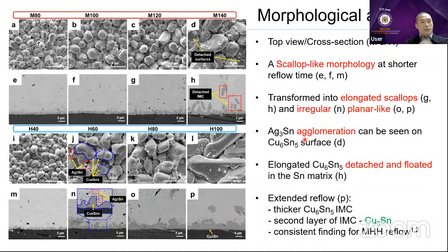Okay, this one is the morphology analysis, a comparison between the medium mode and the high mode. For the high mode, we can see here a very big area, very big grain compared to the medium, right? At the same time, we can see the white powder here, which actually refers to the Ag3Sn, right? And when we run for different times, for sure it starts with a very thin IMC layer here, and it tends to be very thick at the end of the picture, because when we compare 100 seconds to 40 seconds, for sure this is a longer time, and then they will form this IMC Cu3Sn.